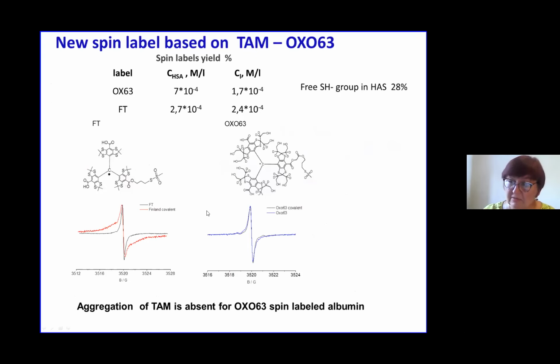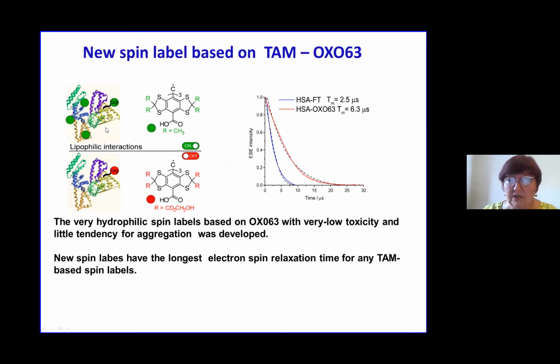What is interesting? We tried to confirm that we developed a new water-soluble trityl spin label. Here you see results for oxo-63, which is covalently attached, and the line is very narrow, and there is no signal of aggregates. While for Finland, we have very large aggregates, which really disturb the experiments. As a result of this work, in the Finland radical many trityls are non-covalently coupled with the albumin, but with oxo-63 everything is fine, and one can measure whatever he wants. In addition, a very nice surprise is that oxo-63 has a very long electron spin relaxation, 6.3 microseconds, which is very nice because it means that one can measure much longer distances than with the Finland radical.